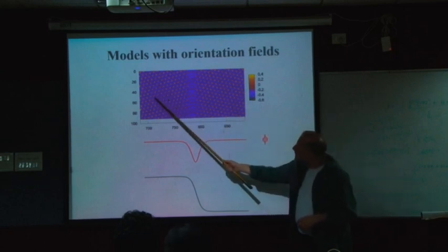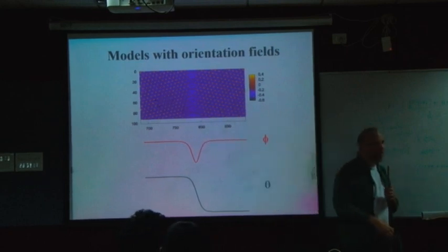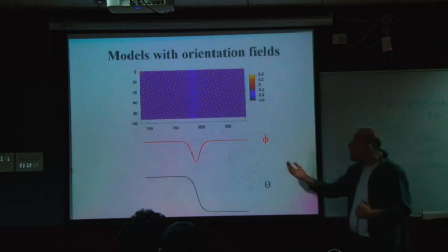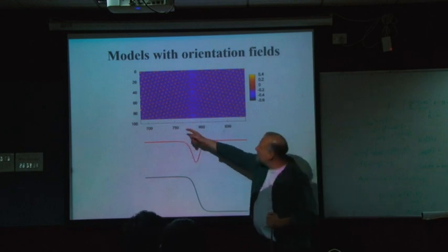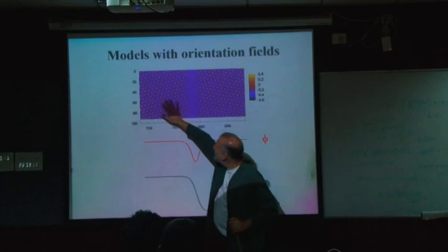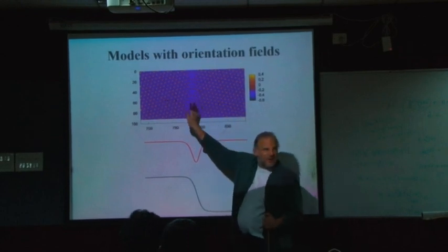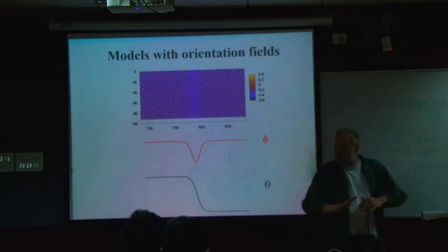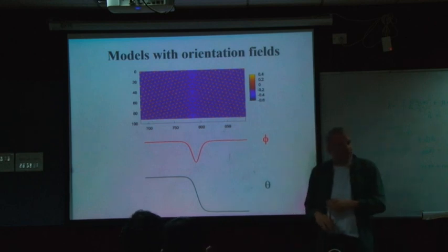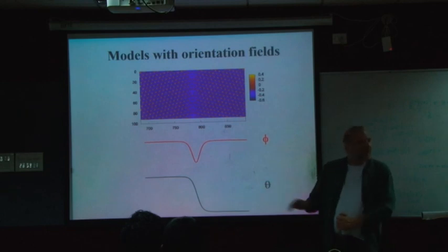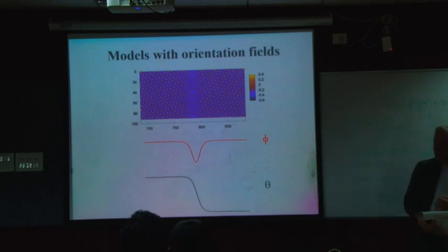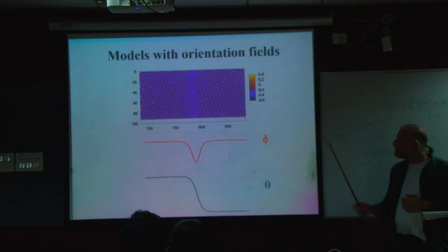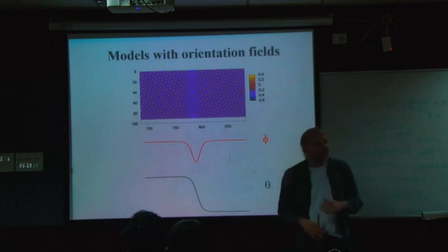So you see here, I have a regular structure, and the way this model works is indeed it produces a triangular lattice of maxima, which you can interpret as a hexagonal crystal. Right? And you can also see that there are two different grains because the crystals are oriented like this here and like this here. So the model is invariant by rotation, so you can create grains in any direction you want. And if you start this from a random initial state, you will indeed get a polycrystal, and you will observe grain coarsening. Okay? Only the simulations are also quite heavy because this is a 6th order differential equation, so you can go to somewhat larger lengths and time scales, but still it's not very big.